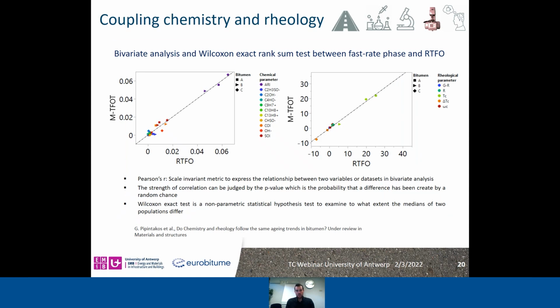Then all these parameters, the rheological and chemical parameters, were implemented in statistical software, and we first compared the short-term aging and the completion of the fast rate phase from the aging chemical paths. And for that, we first performed the bivariate analysis. Here you can see the bivariate analysis for the chemical and rheological parameters. And this allows us to judge if the correlation between two data sets, expressed by the Pearson's R, is strong enough. And this, of course, is supported by the p-value of the Pearson's R, which shows, in other words, the probability that this difference is random or not.